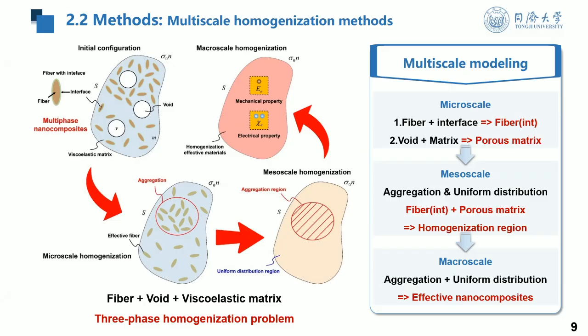And for the meso homogenization, we first consider the aggregation of the nanofillers, because the nanofillers have a non-uniform distribution in the polymer matrix. And then for the microscale, we homogenize the short fiber, the interface, the void, and the matrix. And finally, on the macro scale, we can obtain the mechanical and electrical properties of the nanocomposites. This is our main framework for the multiscale modeling.